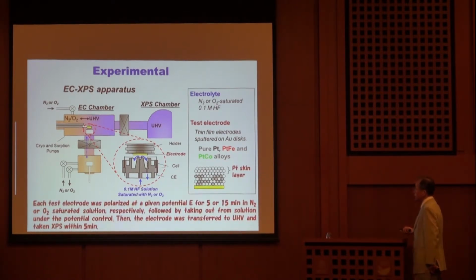And each test electrode was polarized at a given potential here for 5 or 15 minutes in nitrogen or oxygen saturated solution, respectively, followed by taking out from the solution under the potential control. And then the electrode was transferred to the ultra high vacuum system and XPS was taken within 5 minutes.